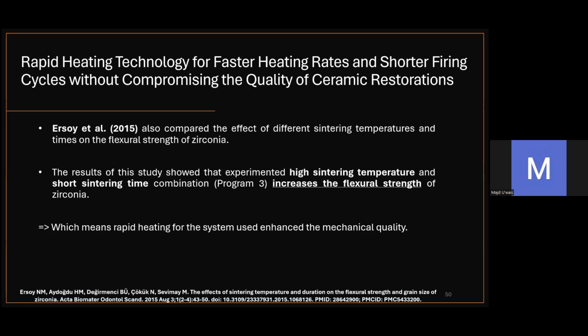Regarding the next topic, which is rapid heating technology without compromising the quality of ceramic restorations, Ersoy and his colleagues also compared the effect of different sintering temperatures and times on the flexural strength of zirconia. The results of this study showed that the combination of high sintering temperature and short sintering time, which is program 3, increases the flexural strength of zirconia, which means that rapid heating for the system used enhances the mechanical quality.